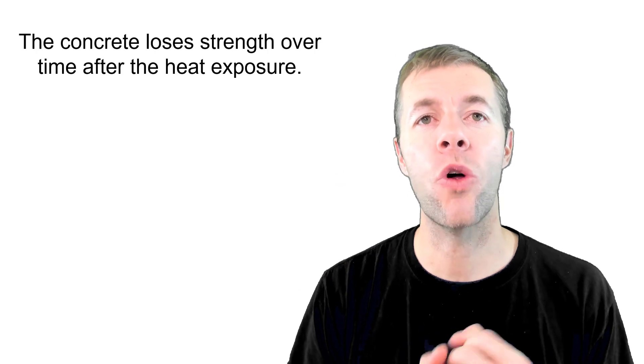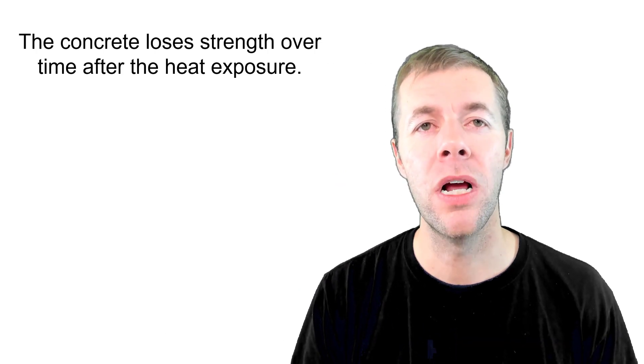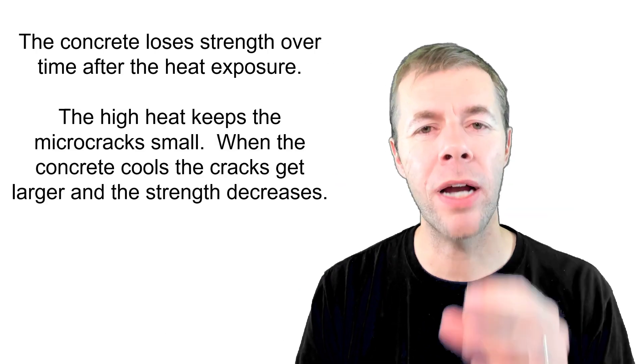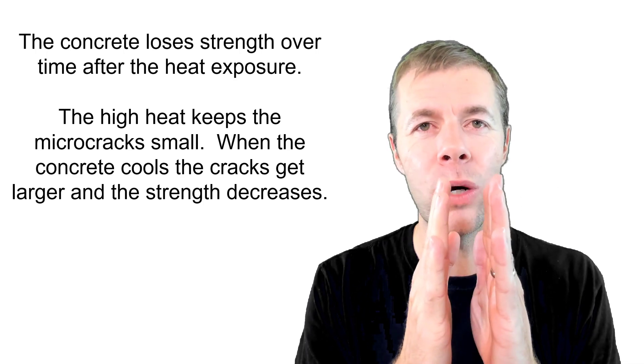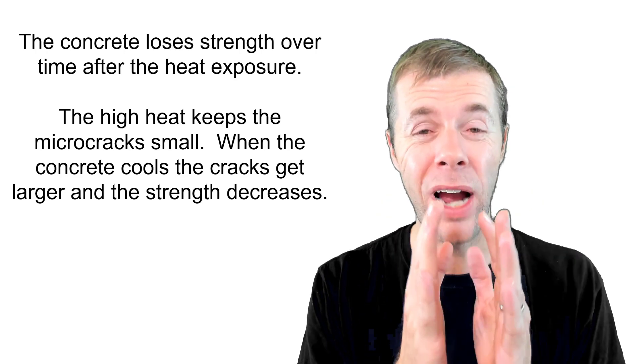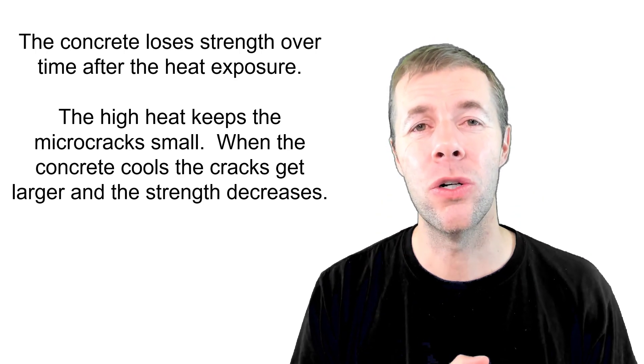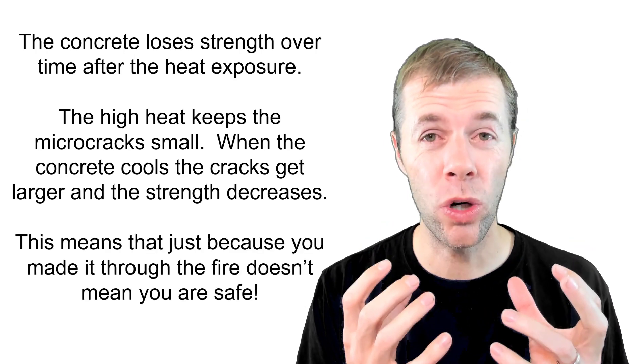Well while these things are hot, again these micro cracks are kind of small. And if you cool them down they can get larger. The concrete is going to lose strength over time after the heat exposure. The high heat keeps those micro cracks small. It keeps them close together. And as the concrete cools they're going to get wider. And as those cracks open up it's going to decrease your strength. And this means that just because your concrete structure made it through the fire it doesn't mean it's safe.